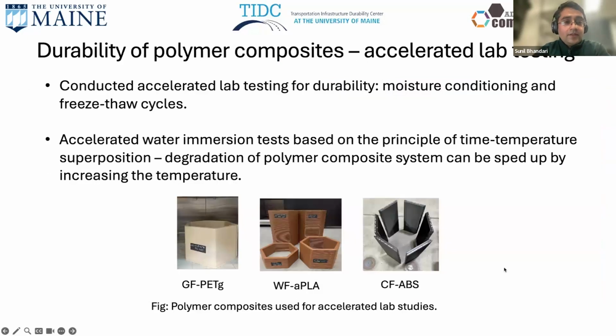So another aspect of this study was to study the durability of the polymers exposed to the conditions at site. So we wanted to see how long these parts will last with acceptable performance. So we conducted accelerated lab testing for durability, moisture conditioning, and freeze-thaw cycles. Accelerated water immersion tests based on the principle of time-temperature superposition were performed. The idea is that by increasing the temperature, we increase the rate of degradation of the polymers in lab.